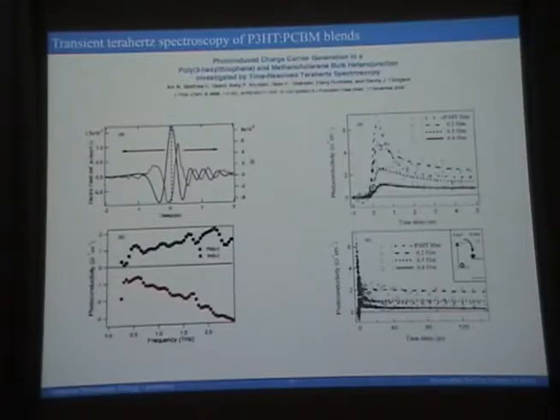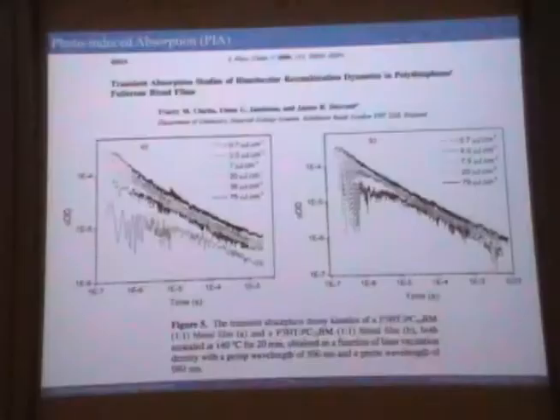Because we know that devices produce many, many more carriers. Lots of people will tell you that there are no carriers produced in P3HT at all, only excitons. That's wrong. But the problem is that the carriers are being produced over long timescales. And you have to look at this tail here to see that the carriers are being produced after the light pulse was used to generate the excitons. They live for very, very long times.